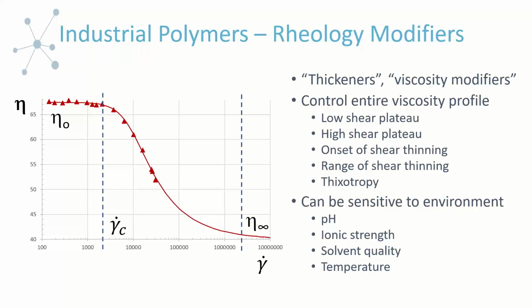And you can essentially also trigger certain behaviors as you change the environment. A lot of these polymers are sensitive to different aspects of the environment. So water-based or aqueous polymers can be sensitive to pH and ionic strength. Ionic strength, both the level of salt and the type of salt, can be very important to the behavior. And if you're dealing with organic systems, then you can adjust behavior by adjusting the solvent quality, using solvents with different solvent quality, so poor to, say, good solvents.